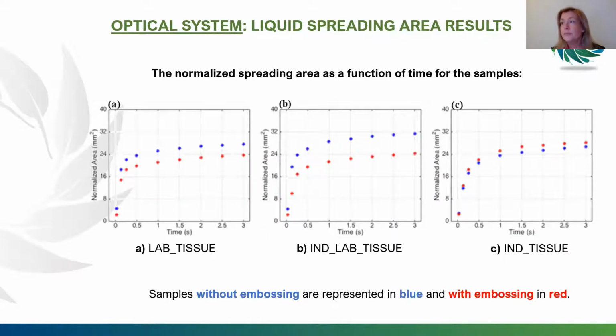The evolution of the spreading area over time is defined by an initial fast kinetics for spreading times below 0.5 seconds, followed by a slower kinetics towards a stabilization value for the spreading area. The effect of the fiber mixture is illustrated when comparing the first two graphics, A and B. Image C illustrates the creping effect.